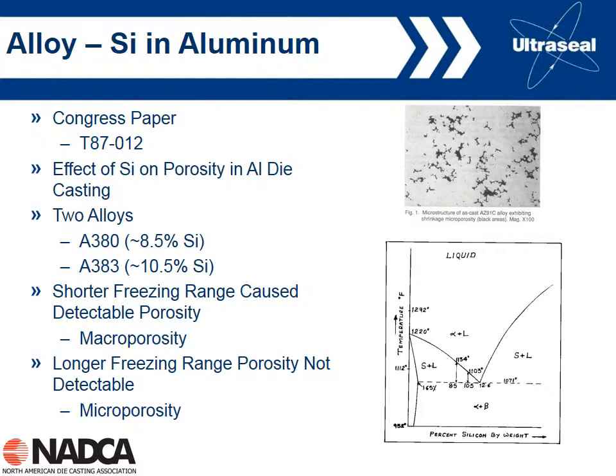And so this can allow us to pass X-ray inspection if we're having problems with a large pore maybe in 383. The iron concentration of the alloy can also affect things. If you have a high iron concentration, during solidification you tend to get aluminum iron platelets coming out in the microstructure. These platelets form pretty early and can block the feeding channels that we've talked about in terms of how we actually feed the shrinkage. And so high iron can also give you high levels of porosity in your castings.